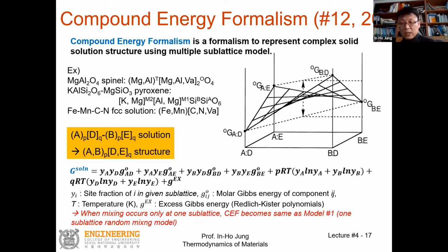However, in FactSage, we typically use coordination number 6 for the pure metallic end member in the liquid solution. And I also told you that one of the advantages of the modified quasi-chemical model, model 98, is that we can realize the random mixing model inside of the quasi-chemical solution model. We assume that the entropy does not change depending on the interaction inside model 98, and then we can realize those kinds of conditions in the quasi-chemical model.